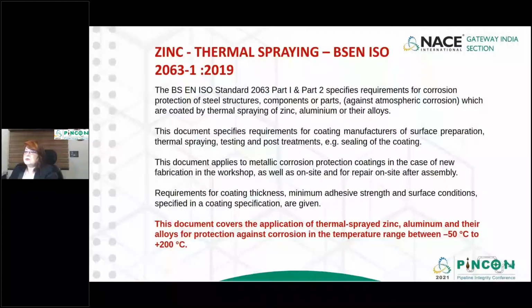As per BS EN ISO 2063 standard, it specifies the requirements of corrosion protection coating by thermal spraying of zinc, aluminum, or their alloys in case of new fabrication in the workshop, as well as on site and for repair on site after assembly. Also for coating, manufacture, surface preparation, thermal spraying, testing, and post treatments, as for example sealing of the coating. Requirements for coating thickness, minimum adhesive strength, and surface conditions specified in a coating specification are given. This document covers the application of thermal spray zinc, aluminum, and their alloys for protection against corrosion in the temperature range between -50 degrees centigrade to +200 degrees centigrade.